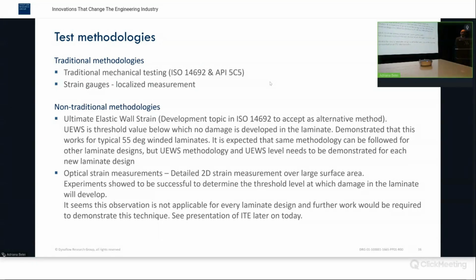Then some short information on the test methodologies. So for this project, we mainly used traditional mechanical testing, as was prescribed in, for instance, ISO 14692 and the API 5C5, using strain gauges for measuring the strain. We did look at non-traditional methodologies like the UEWS and optical strain measurements. For the UEWS, we decided not to take that into the guideline at the moment. The ISO 14692 committee is currently looking at introduction of the UEWS methodology. That's a direct measurement method where you can directly measure the threshold levels. So then you don't need to work with these scaling exercises.